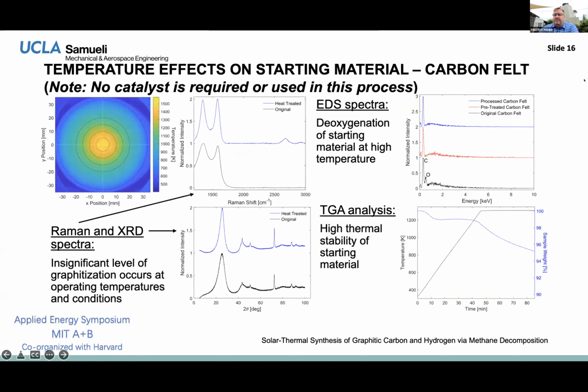The starting material that I've mentioned a couple of times, instead of being a flat piece of graphite, which we used for calibration, is now carbon felt. This is a porous material made of PAN carbon fibers, for those of you who work in composites. And I think it's very important for me to say there's no catalyst. Not even the carbon is a catalyst. I'll talk about that later. There's no catalyst in this process. A lot of times when I give a talk like this, people will say, well, what was your catalyst? Because almost everybody uses catalysts in methane decomposition. We don't have any. There is none. And that's an important feature of this work.